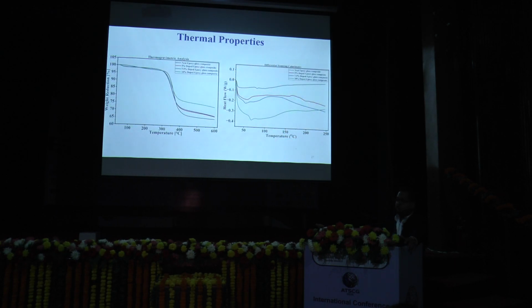This is the thermal properties of our composites. As you see from the previous curves, we can observe that all doped composites show improved thermal stability compared to the neat epoxy glass composites. In the curve, we can see that the main degradation occurs between 320 to 400 degrees centigrade, corresponding to epoxy decomposition. The doped samples exhibit slower mass loss and higher residual char, confirming enhanced condensed phase flame retardant action. Among all formulations, the 7.5% and the 10% doped show higher char yield, indicating effective phosphate-induced carbonization and nanofiller barrier effect.